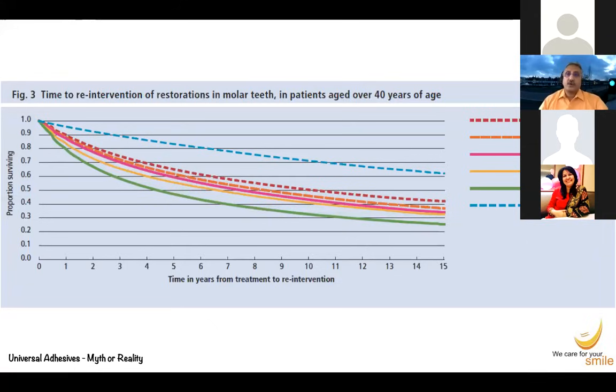Now, if you look at patients over 40 years of age, this is very important for me because glass ionomer is one of the materials which is recommended in older patients, especially in geriatrics. But here you also see that the failure rate with glass ionomers, or the need for re-intervention, is much higher. Again, crowns perform much better, and composites are somewhere in the middle. Also important to note, MOD restorations generally don't do very well. I mean, that's common sense. The more tooth structure and the more margin you remove, the more the likelihood of you needing intervention.